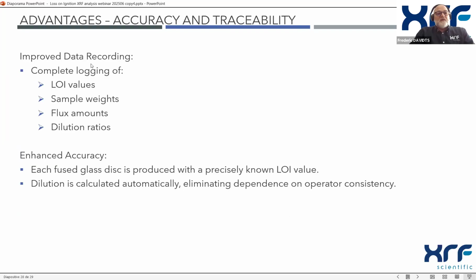Also, we improve the data recording because we have a complete logging of the LOI value, the sample weight, the flux amount, and the dilution ratio. And we also gain in accuracy because each fused glass disc is produced with a precisely known LOI value. And of course, that's really good. The dilution is also calculated automatically, eliminating the dependence on operator consistency.